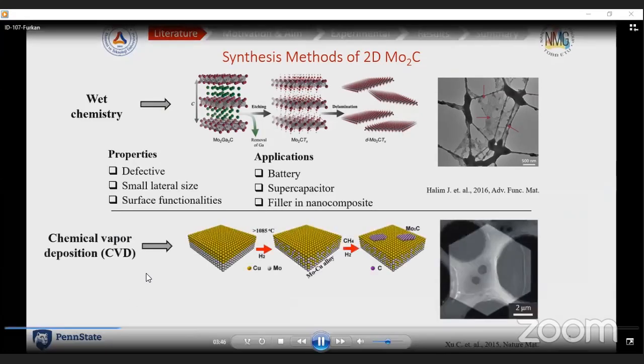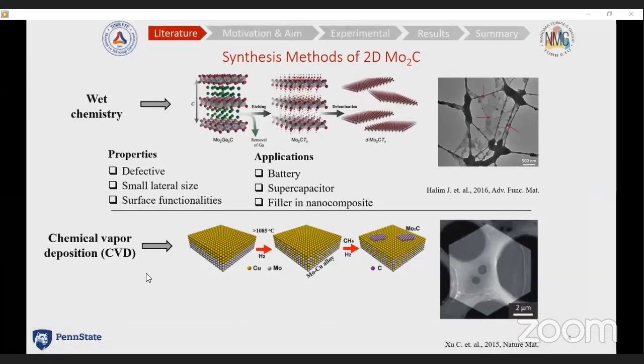So in the other method, the 2D molybdenum carbide can be synthesized by chemical vapor deposition. In this method, first you have a copper foil on top of a molybdenum foil, and at high temperatures, at about the melting temperature of copper, a molybdenum-copper alloy forms. So therefore, molybdenum atoms diffuse to the surface of the copper after the saturation.